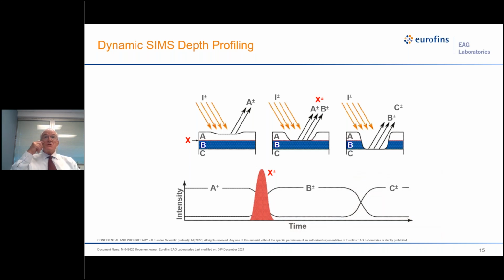So in a depth profile, many of you ask, what is a depth profile? How does it work? If we have our primary beam here, sputtering the sample and digging a crater, positive and negative ions are being emitted. Since the surface is still in material A, we have a profile for A right here. If you sputter a little further, until the surface reaches this interface layer of X, now we start to get a signal for X. As the profile goes further, the X goes down and we're sputtering in the B layer until we hit the substrate C, and then the B layer goes down and the C comes up.